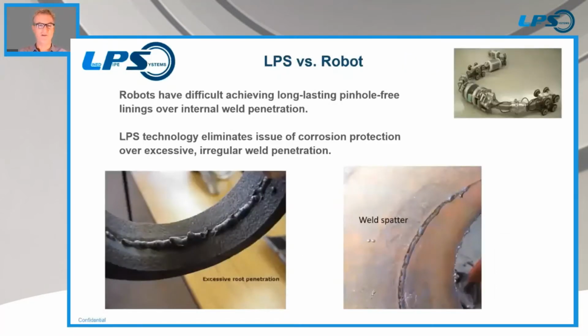So first off, our technology as compared to the robot. Robots have a number of quality issues, and one of them is the fact that they've got to paint over internal weld penetrations, which can be very challenging. I've spent a lot of time trying to get welds pinhole free inside of tanks and pipes in my career, and that's when you can actually see them. And I'm sure the robot has access to them, and they've got the video cameras. But the problem is that not all weld penetrations are the same. And with their system, they really need to have very smooth weld penetrations. Otherwise, it's nearly impossible to get a pinhole free lining.